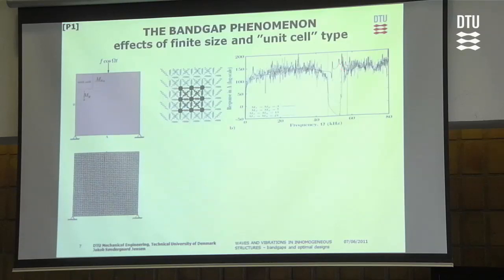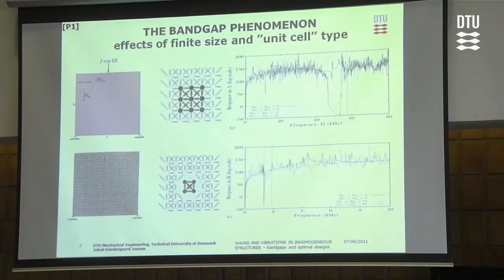Curiously, there is a large vibration level inside — this is due to waves being able to travel along the boundaries of the structure. We can also manipulate the unit cells to move the low-vibration frequency range lower by creating a unit cell with a very heavy inclusion in rubber-like spring surroundings, enabling a band gap near the local resonance frequency of the resonator.